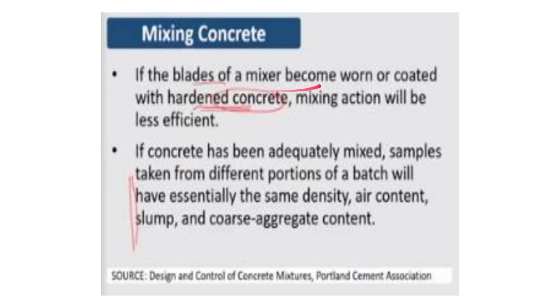If the blades of a mixer become worn or coated with hardened concrete, mixing action will be less efficient. So efficiency will be a question if the blades are not proper, if they get worn off or coated with hardened concrete. If concrete has been adequately mixed, samples taken from different portions of a batch will have essentially the same density, air content, slump and coarse aggregate content. So this is obvious. If it is mixed adequately, concrete will be homogeneous. Therefore, all the basic properties like density, air content, slump, coarse aggregate content will be the same from wherever we take it out.